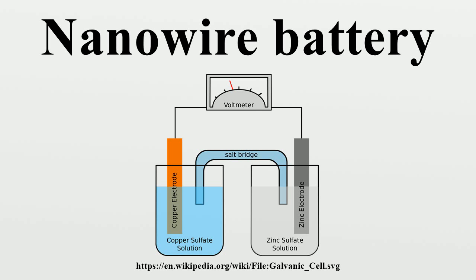Researchers also demonstrated the possibility of sustaining 85% of initial capacity after cycling over 6,000 times by replacing the nominally undoped silicon anode with a double-walled silicon nanotube with a silicon oxide ion-permeating layer as coating.